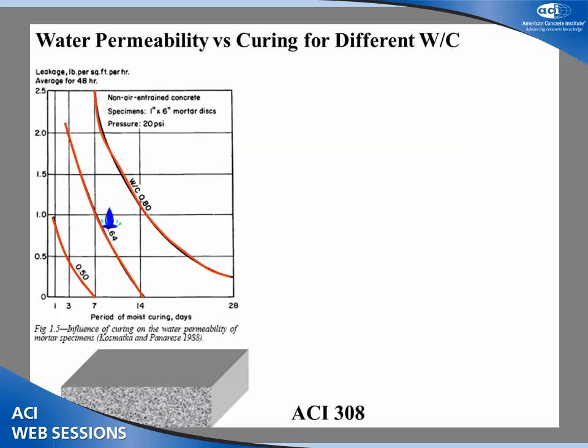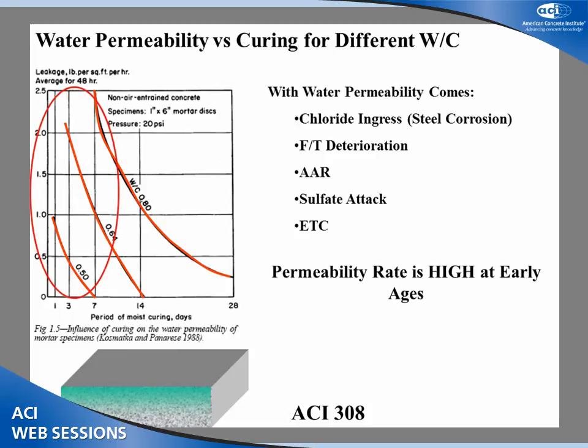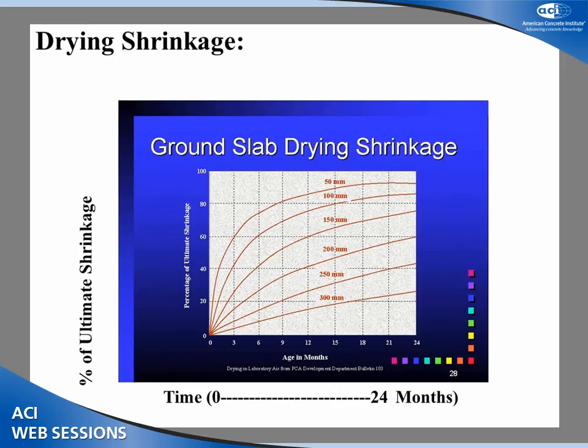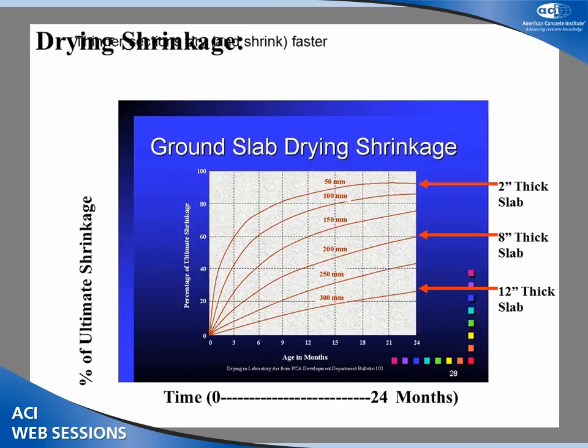Permeability. This shows water permeation with respect to time for different water cement ratios. Look at this guy, high water cement ratio, it's a sponge. With water permeability, a lot of bad things happen. Chloride ingress, freeze-thaw deterioration. Drying shrinkage, it changes with respect to time, it eventually slows down.